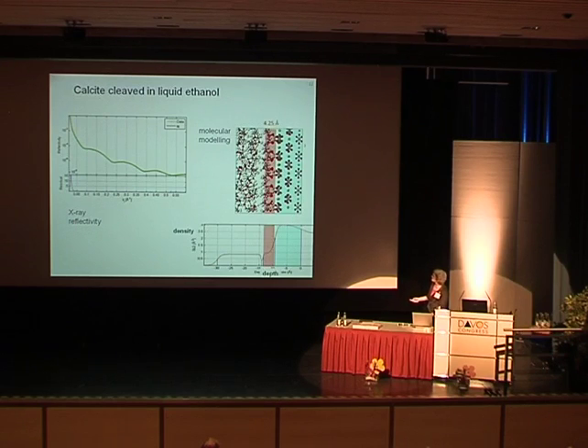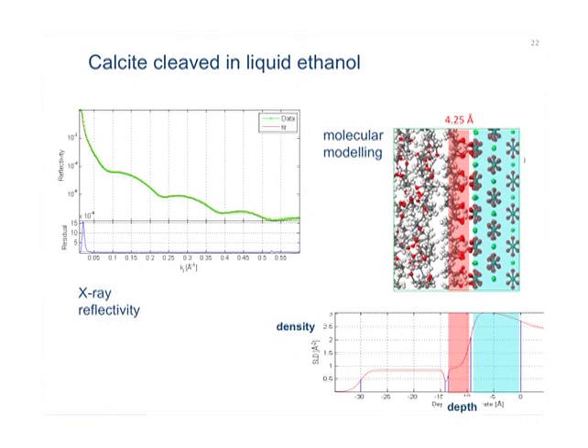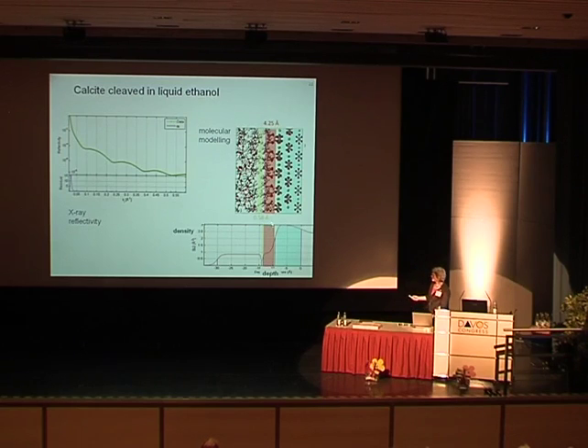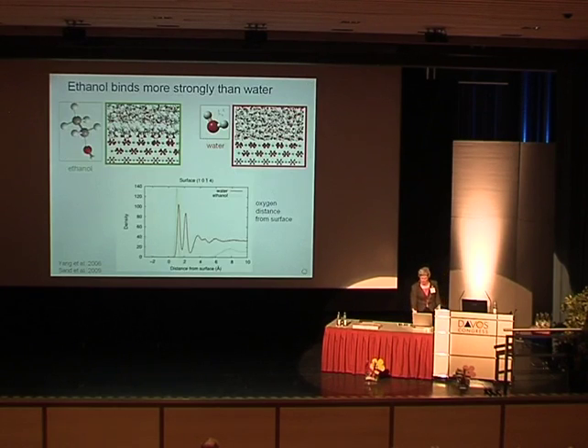And then we have a layer of ethanol attached, and we can see that. And then we have an area where there's not very much at all, and we can see that in our experimental data. And then we have the bulk ethanol out here, and there it is there. And this bulk ethanol is on the order of 20 angstroms thick. So we have a very tightly bonded ethanol layer, and then the rest. And ethanol is even more strongly bound than water.